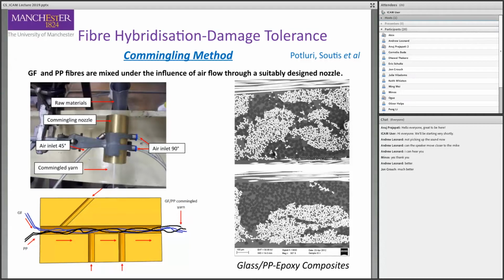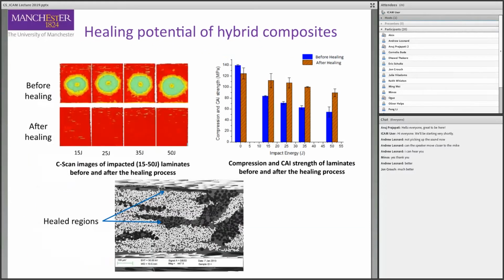Eventually, it will get damaged, and under an impact event, you will have the same damage modes, the matrix cracking and delamination and so on. But now the composite enables you, if you hit the composite, to melt those polypropylene fibers. They can fill those matrix cracks and delaminations. And then when you look at the compression after impact, we have recovered quite a lot of the original strength of the laminate.